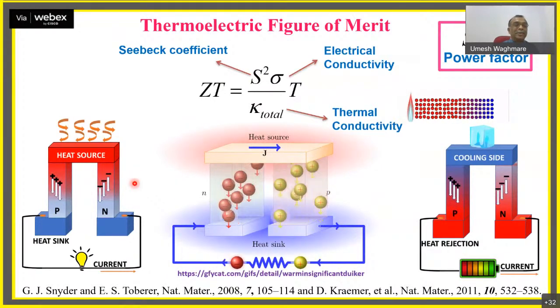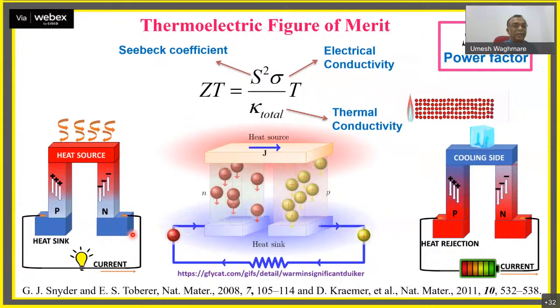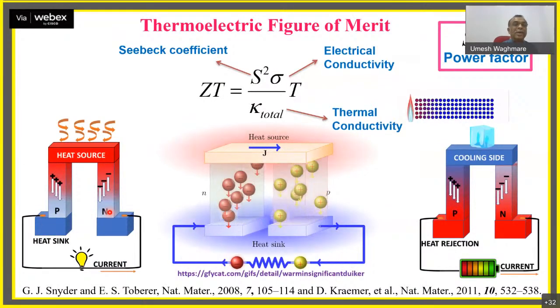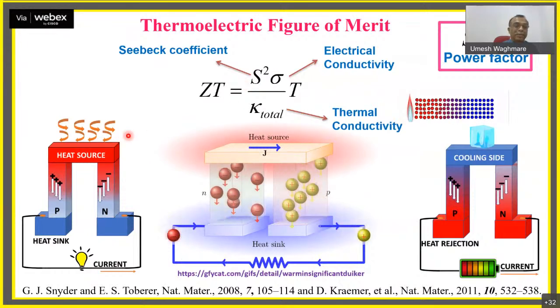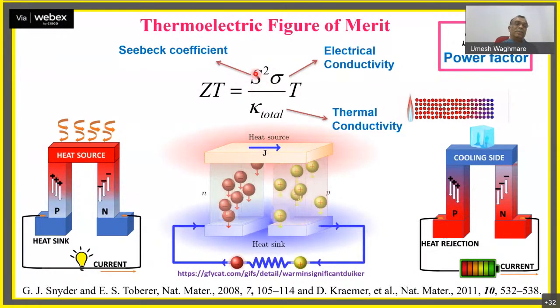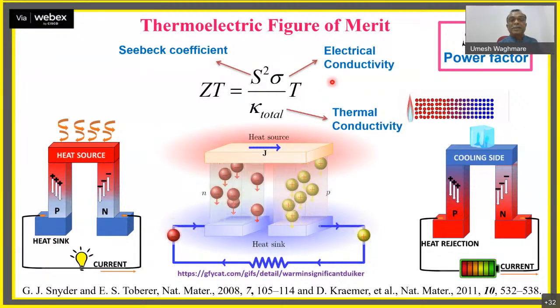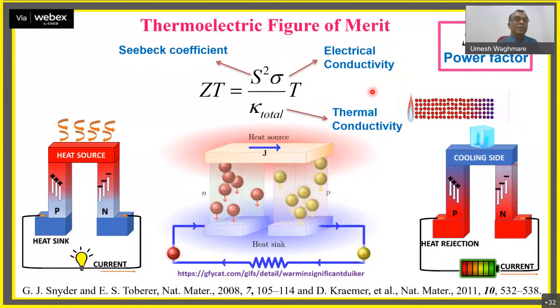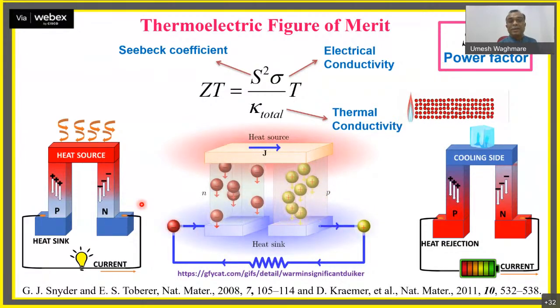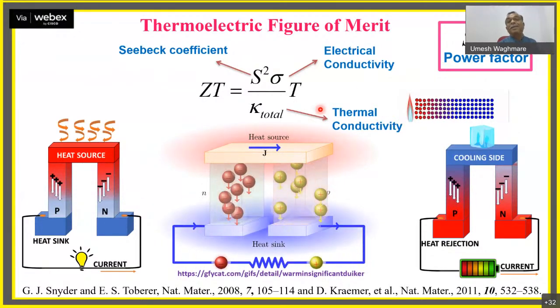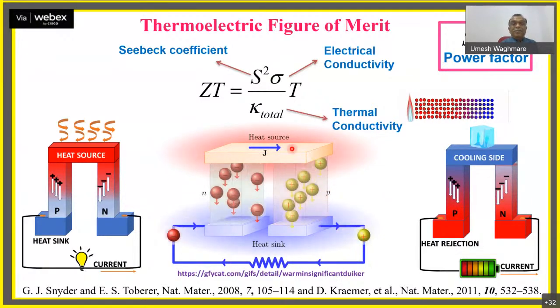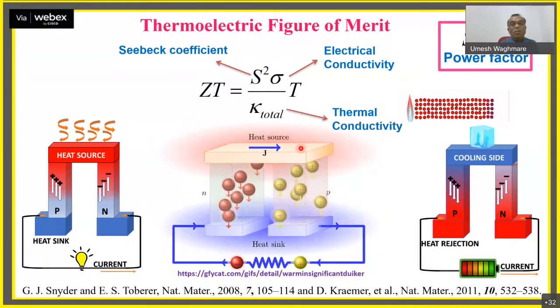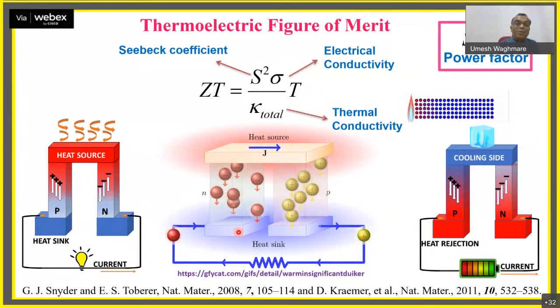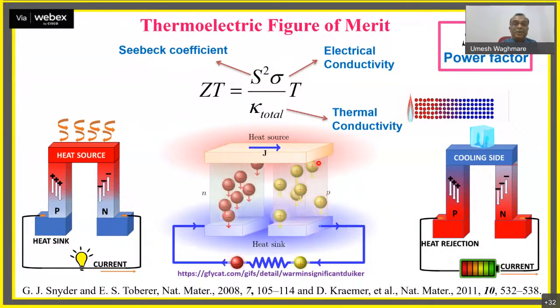A thermoelectric is a material that, if you sandwich it between a heat source and a heat sink, can generate electric voltage. And that voltage is proportional to the temperature gradient you have, and that constant is the Seebeck coefficient. So the larger the Seebeck coefficient, the larger the electrical voltage you would generate across this. Next, electrical conductivity is very important because the material should carry the electrical current very efficiently, but not the thermal current. See, this is the key. If the material carries heat very efficiently, most of the waste heat will be carried to the heat sink or the cold part of the body, right? And that will not be an efficient thermoelectric.